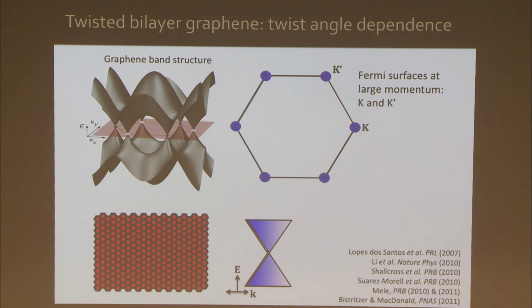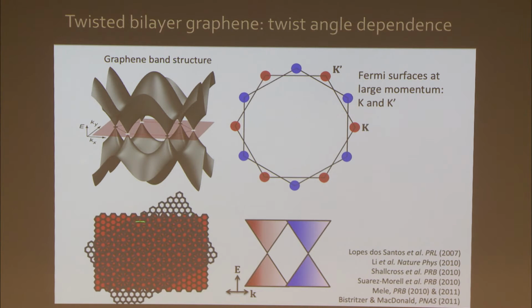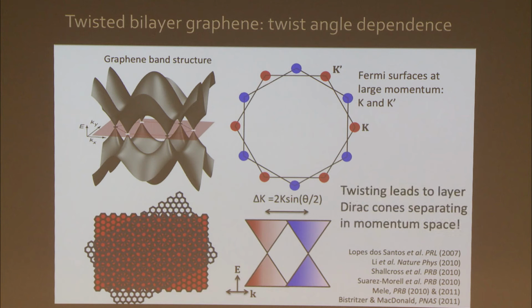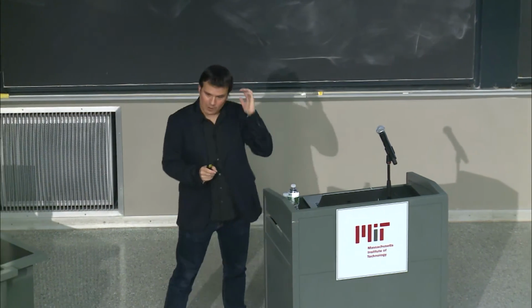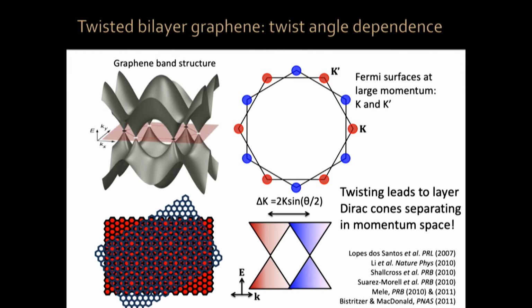Now, let's twist a little bit, okay? So let's rotate the two graphene sheets in real space, the reciprocal spaces or the momentum spaces also rotate by the same angle. Okay? That means that the Dirac cones of layer 1 and layer 2 separate, and they separate by a distance in momentum space which is proportional to the sine of half the angle. Okay? So this twisting leads to the layer Dirac cones separating in momentum space. Now, for what I want to show you in a moment, it's good to start with a small twist angle, so that the sine of the angle is the angle. Okay? So let's start with that.